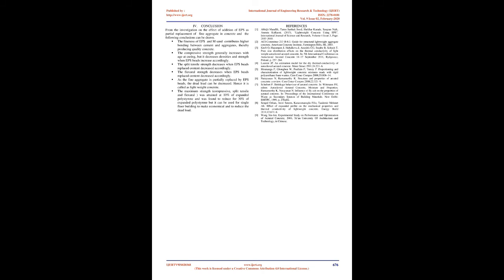Conclusions: From the investigation on the effect of addition of EPS as partial replacement of fine aggregate in concrete, the following conclusions can be drawn. The fineness of EPS and M-sand contributes to higher bonding between cement and aggregates, thereby producing quality concrete. Compressive strength generally increases with age at curing, but decreases in density and strength as EPS bead content increases. Split tensile and flexural strength both decrease when EPS bead replacement content increases. As fine aggregate is partially replaced by EPS beads, dead load can be decreased — hence it is called lightweight concrete.